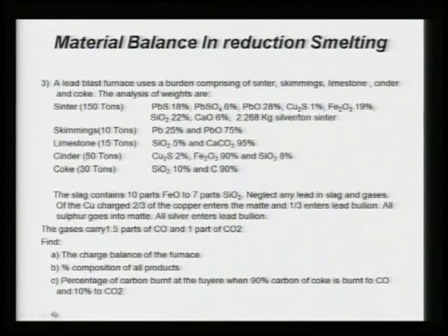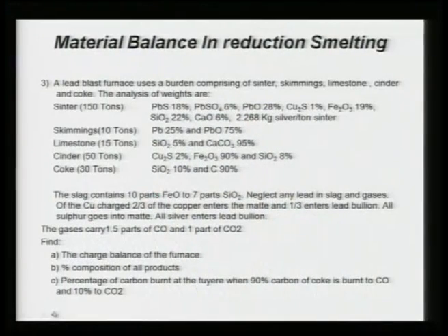So, many a time in the plant, to improve the economy of blast furnace smelting of lead ore, the skimmings are recycled to recover lead. You may recycle them in the blast furnace as a feed or elsewhere. The whole idea is that you do not want to lose lead. So, here the sinter, that means the roasted ore, is 150 tons, then skimmings, limestone, cinder and coke are all the charge, and all these five constitute what is called the burden. The burden consists of all these things.